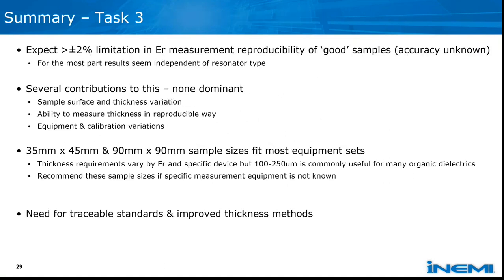So, the summary of task 3: don't expect anything better than plus or minus 2% in dielectric constant measurements, and that really is a reproducibility number in the best case situation. There are a number of contributions to this, and none of them are totally dominant, so we need improvements in several areas to squeeze the performance out of this. We did find that, barring information about a particular lab, using samples that are 35 by 45 or 90 by 90 tends to fit most equipment sets. The thickness varies by dielectric constant and the specific device you're measuring with, but typically 100 to 250 microns is commonly useful for many organic dielectrics. So if you don't know exactly where you're going to get your measurements done and you're asked for a dielectric sample, your best bet is to request something in the 100 to 250 micron thick range, in the 35 by 45 or 90 by 90 form factor.